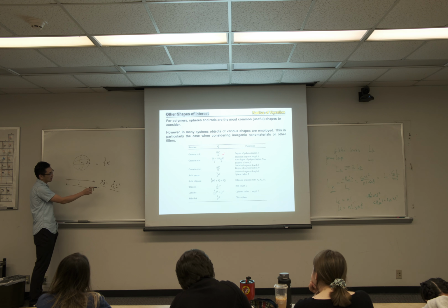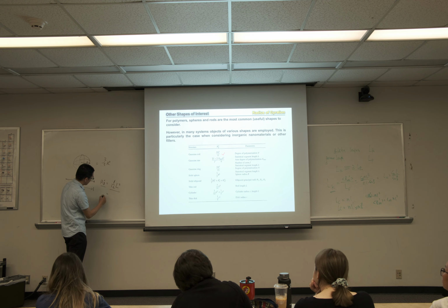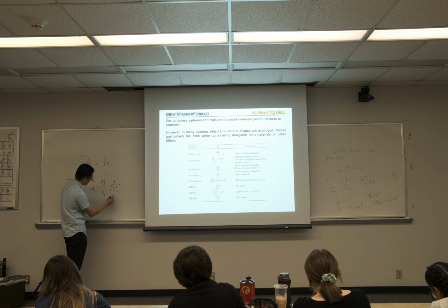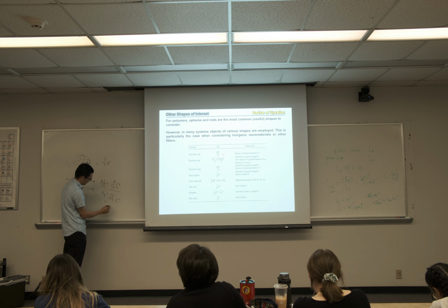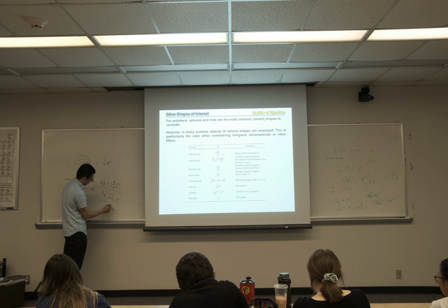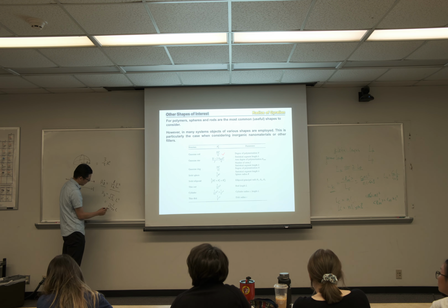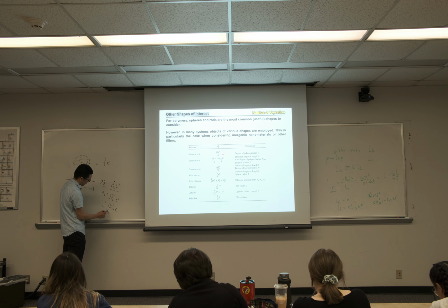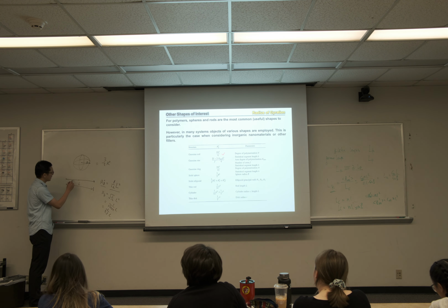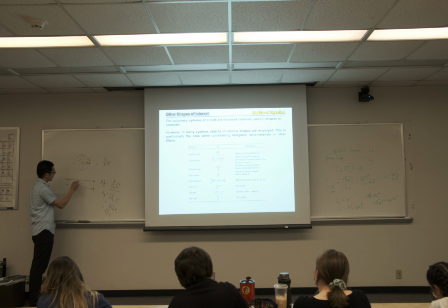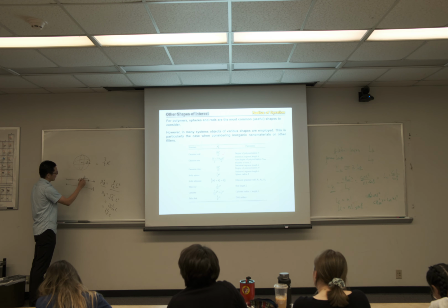So that should be roughly, RG would be 1 divided by root 12, so roughly 1/3 of the length. So the radius of gyration would be roughly 1/3 of L. So this would be the RG, if this is the mass center, okay? Gives you some idea.